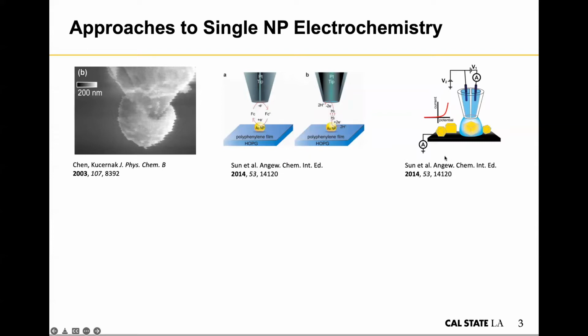Other traditional electrochemical techniques involve the scanning probe microscopy techniques, such as scanning electrochemical microscopy and scanning electrochemical cell microscopy. So for both of these techniques, it's still based on electrochemistry, based on current measurement, but they're using a nanoelectrode to scan over the surface. So as a result, you can get a spatial resolution of the sample for different nanoparticles present on the surface.